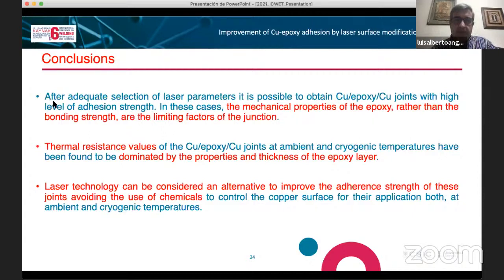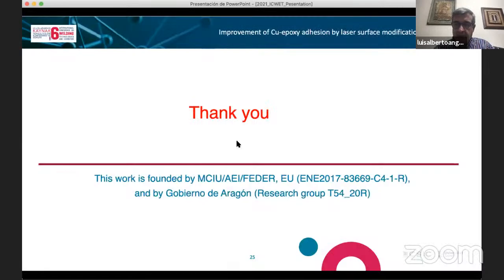So just to finish, I want to say that after the adequate selection of the laser parameters, we can control the mechanical reliability of the junctions, and the mechanical properties are limited by the mechanical properties of the epoxy, rather than the bonding strength. And it's important that in this case, the thermal resistance value of the joints is limited by the thickness of the epoxy layer, and in consequence, the laser technology is a good alternative to improve the adherence strength of these joints, avoiding the use of chemicals. And thank you.